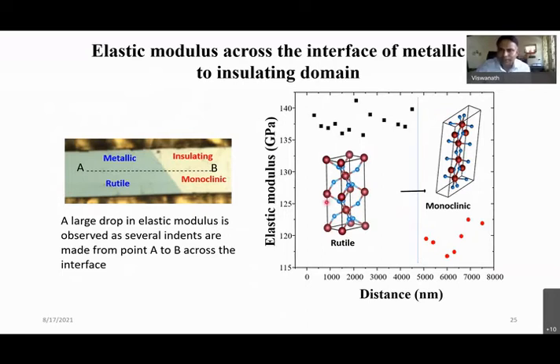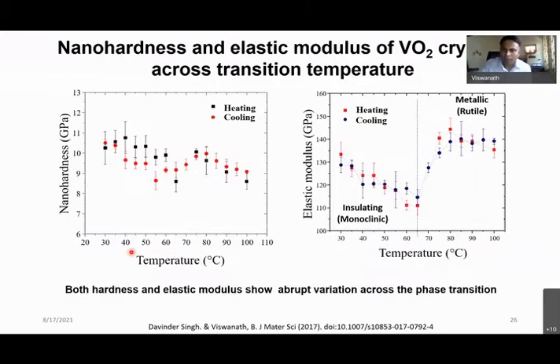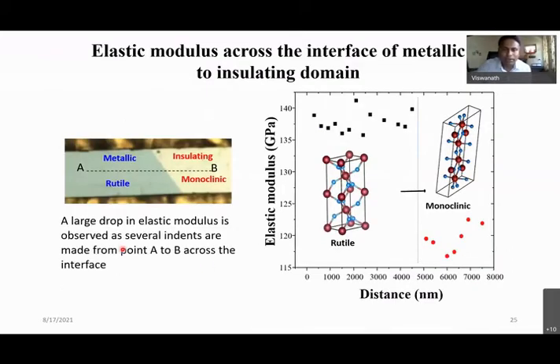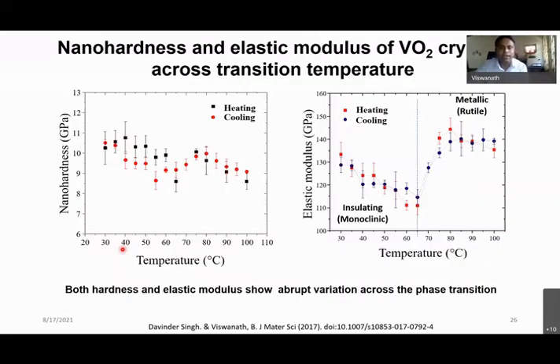At constant temperature, we have the elastic modulus abruptly changing when going from the rutile phase to the monoclinic phase. So we could clearly cross-verify, both by the elastic modulus as a function of temperature and by holding the same temperature and measuring from the metallic and insulating domains. We are able to get relatively consistent measurements. I would say the scattering is slightly more when you measure just as a function of temperature, because sometimes we don't know the place we are trying to measure. Probably it has already transformed or is very close to the interface. I would say the other measurement is a little more reliable, without the phase boundary and the complication of the phase evolution.